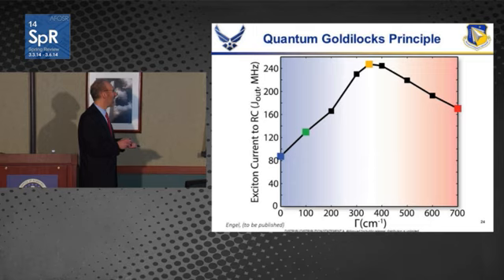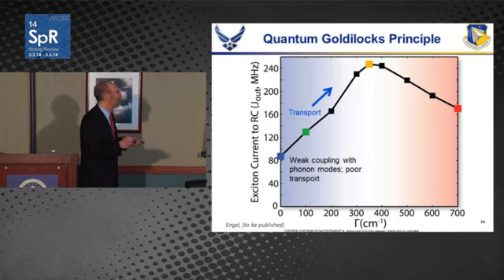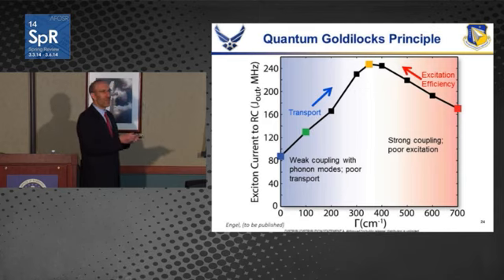These are some calculations by Greg Engel, showing the optimum way in which we want this material to interact with its environment. What we show here is coupling between the material and its environment, the phonon modes of the environment. If we have very weak coupling, we can excite this molecule, but the energy won't transport. It's not coupled well to its environment. As we increase the coupling, we improve transport. But if we go to the extreme of very strong coupling, then that energy no longer stays in the molecule. We can't absorb energy in the molecule. The oscillator strength is spread out in the classical view. So we have to reduce the coupling to improve the excitation efficiency.